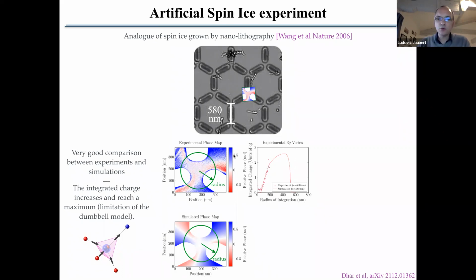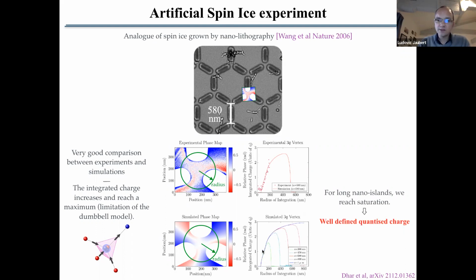And in experiments, we could not go to large enough radius, but the match between experiments and simulations tells us that we have this well-defined magnetic charge there. And just to confirm it, we did simulations with longer and longer nano-islands. So the same geometry of the lattice, but the nano-islands get thinner and thinner, which means that the vertices get further and further away. And as you do that, you see that the maximum is reached at longer and longer radius, and at some point you reach a plateau, which corresponds to the theoretical expectation value of 3Q, because you have three spins pointing in. So inwards, inwards, and inwards, which means that with the dumbbell model, it's as if you had free magnetic charge in the middle here. So you expect this 3Q vertex here. And that's the value you can reach if you have infinitely thin nano-islands.